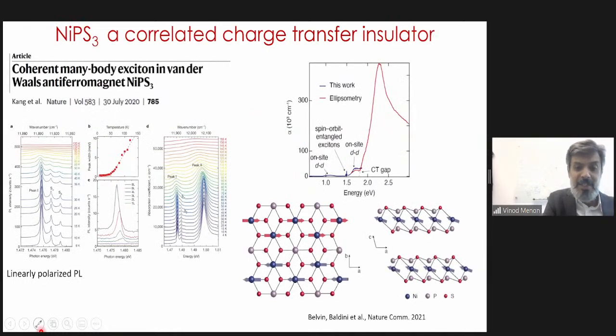And so in that vein, one of the first things that we have done recently is we've looked at a material called nickel phosphorus trisulfide. Don't worry about what this material is, but this material is not a semiconductor. It's actually an antiferromagnetic material. It's actually a correlated insulating material, and it turns out this material also hosts excitons. And this was a paper that came in 2020 where they showed that these excitons are coherent excitons. Their line widths are on the order of 300 micro eV, so extremely narrow, and they emit light with a polarization that is perpendicular to the spin chains inside this material. So these are nickel atoms, and the purple ones are phosphorus atoms, and the sulfur ones are shown in red.